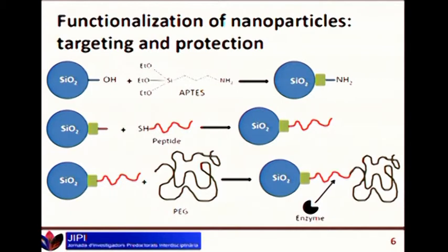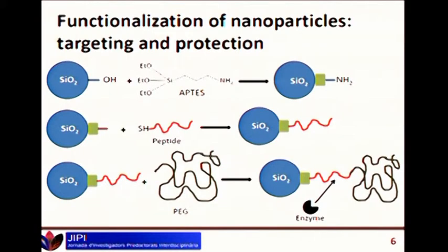So with a peptide, we put a peptide in between the silica nanoparticle and the polymer, with a specific sequence of amino acids. This sequence will be recognized by an enzyme that will be only present at the wound site. That will be a factor; we use activated factor 10. So the enzyme will cleave the peptide here, release the PEG, and unmask the procoagulant surface. So it will be active again.